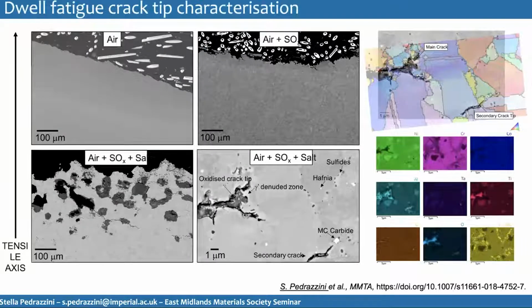So what we found from this test is in air, this sample cracked at 45 degrees. So this is the tensile axis looking up into the slides. The sample cracked at 45 degrees. Once we added SO2 and SO3, a mixture of the two, and this was done with a platinum catalyst to bring it to equilibrium between the two molecules, the fracture was now flat on the surface, so we can see that the mode of fracture has changed.